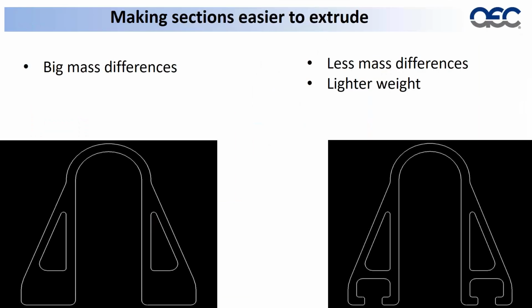So here's an extrusion that comes in as a hollow with 2 mandrels and a fairly deep tongue. As we look at the one on the left, number one, it's going to make the extrusion difficult because the large masses, the hole of the aluminum, will want to go through the place of least resistance, which would be the large mass. With 98,000 pounds per square inch pressure, it can shift the mandrels in the upward direction. But most importantly, what it says to me is that somebody is going to do some machining on this mass after they've received the extrusion.